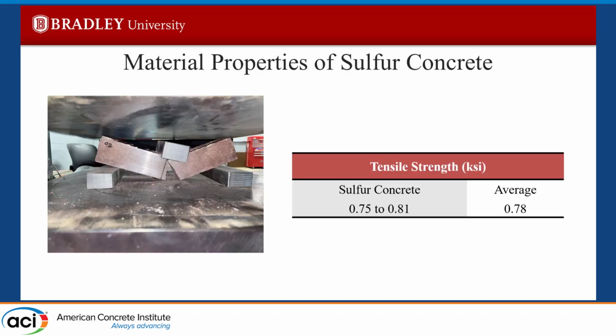And then here we have the tensile strength for sulfur concrete, which is a range of 0.75 to 0.81 KSI, average of 0.78 KSI. So we're expecting around 10% of normal concrete compressive strength for its tensile strength. But in this case, our sulfur concrete was reaching around 15% for its tensile strength. This is just for sulfur concrete by itself. Just throwing out some little facts about it. All of these were calculated using the flexural test.